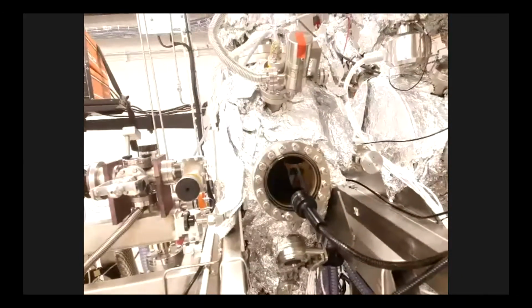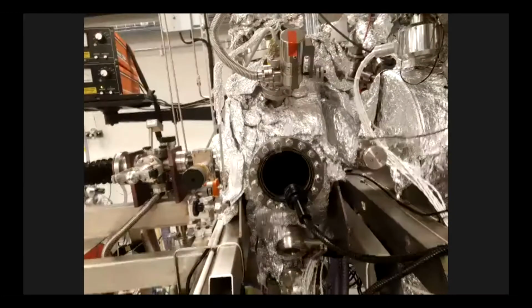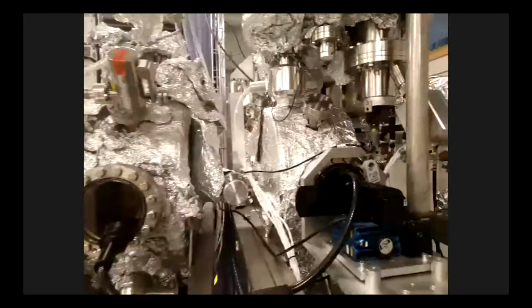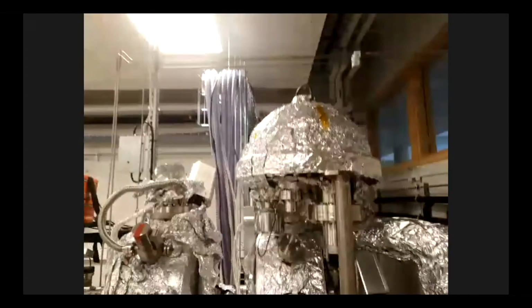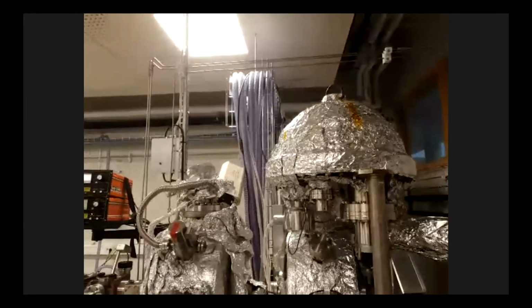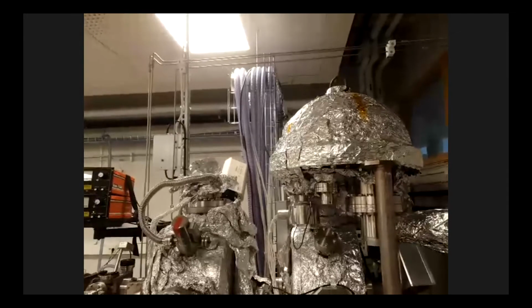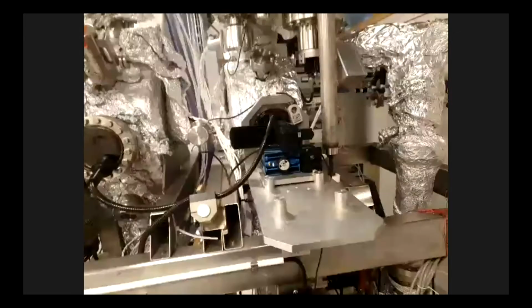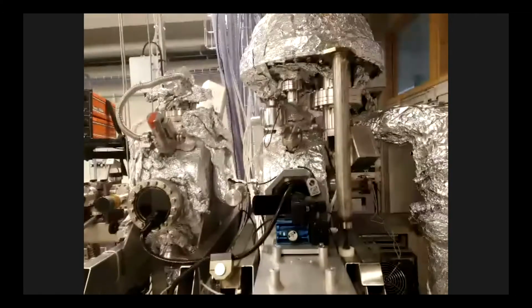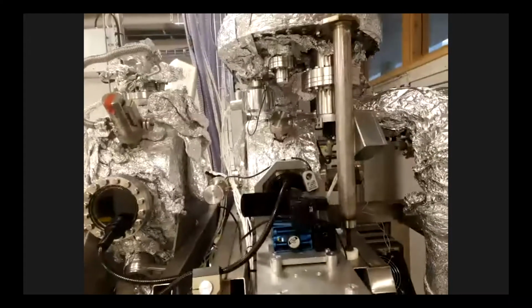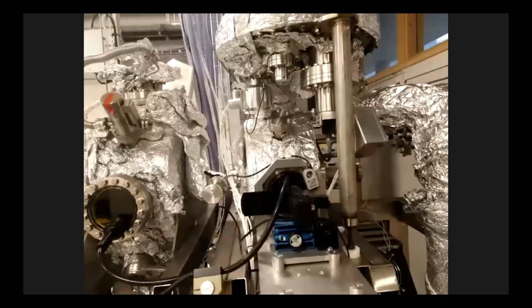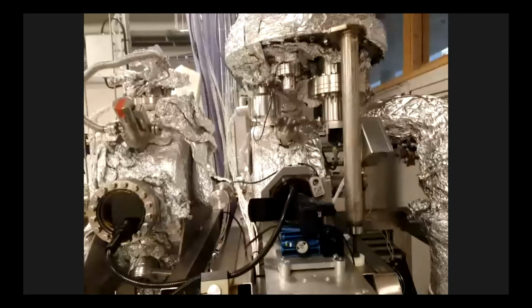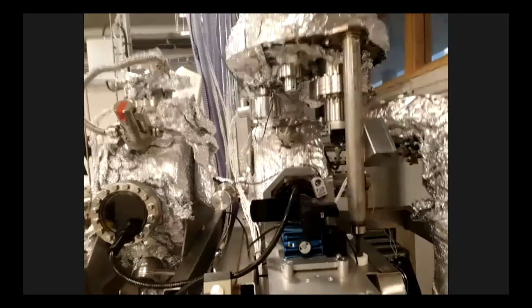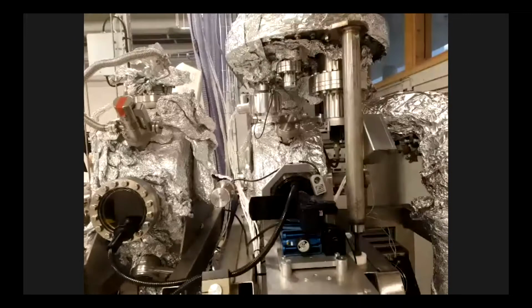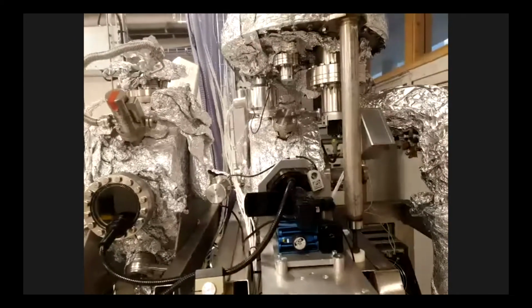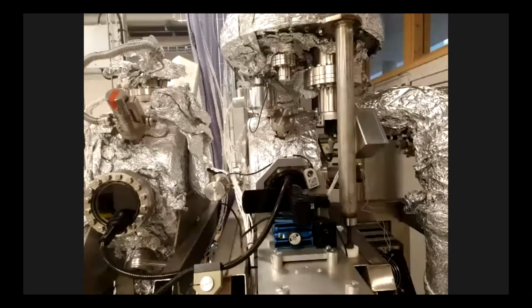And when we're done in there, and now we're talking a pressure of about 10 to the minus 9 to 10 to the minus 10 millibars, we move into the analysis chamber that is connected to the analyzer, which is basically a bandpass filter to measure kinetic energy of the electrons coming out. And the trick is we have either an X-ray source or a helium source that provides photons of specific energy. Those photons are absorbed in the material, emitting electrons. We measure the kinetic energy, and knowing the photon energy, we can then calculate the binding energy of the materials.